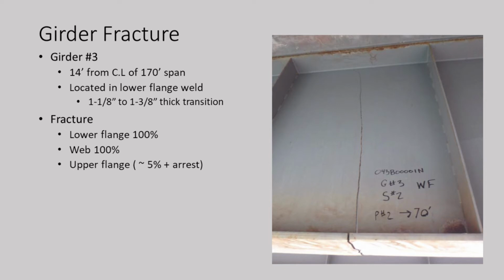It was located in this area. There's a thickness transition from 1 1/8 inch to 1 3/8 inch. There's a weld in there in that lower flange. And then we can see the crack ran pretty straight this time, and it hit this flange-to-web fillet weld up here, jumped that, and went a little ways into the upper flange, and it arrested.